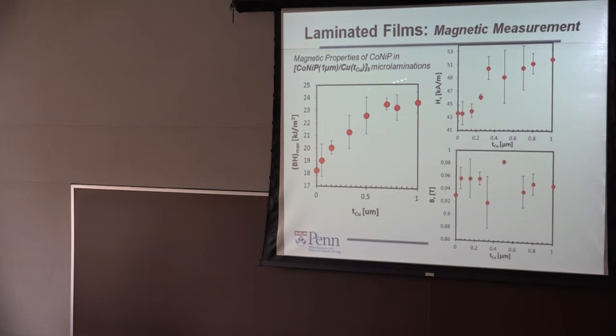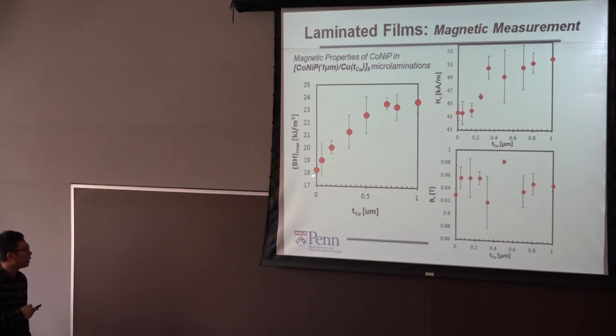Of course, we also did the magnetic measurement by VSM on this 5-pair lamination. Interestingly, you can see that both the energy density and the coercivity increase as the thickness increases, but the remanence stays relatively constant, within 7%. I want to draw your attention to this specific point. There's a very important implication here: this is where the copper thickness equals 0. What this means is that the robot pulls up the thin film every 1 micron, 5 times, because it's a 5-pair lamination. So purely interrupting the electroplating periodically doesn't help to increase the magnetic property. What's really important is the planarization effect from the interlayer.